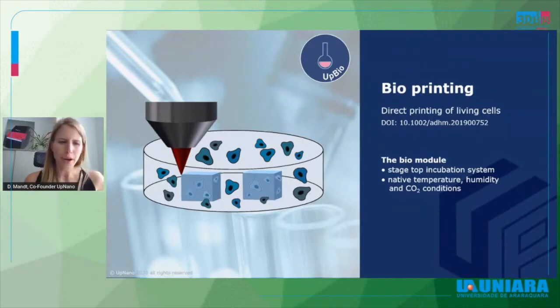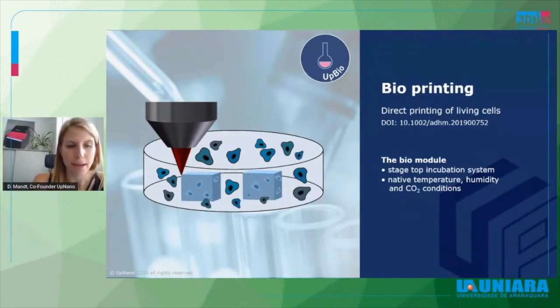When doing bioprinting approaches, we strongly recommend to use the incubation module or the biomodule, so that you have the stage top incubation system where the CO2, the humidity, and the temperature can be adjusted and controlled during the printing process. And Alexander Ovsyanikov and his group have shown several times already that with this setup and these materials, you can achieve really high resolution 3D printing approaches and realizing them.